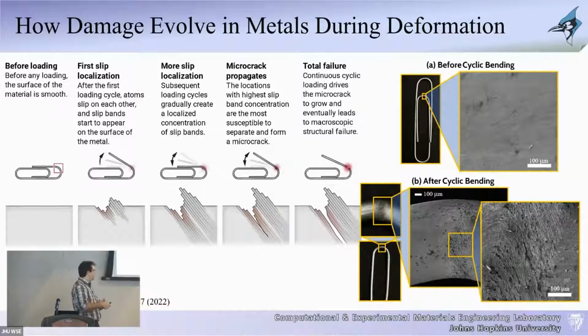It's the cheapest example, you could do a fatigue experiment in your lab, in your office. Get one of these paper clips and just start bending it. Typically, before you bend them, the surface of the paper clips is quite pristine, quite flat. As you continuously bend it, the surface where you're doing that bending starts roughening. And that roughness continues to increase with increasing numbers of cycles until eventually a crack nucleates and propagates and leads to failure. This is actually an experiment that one of my students did as an example just to show this.